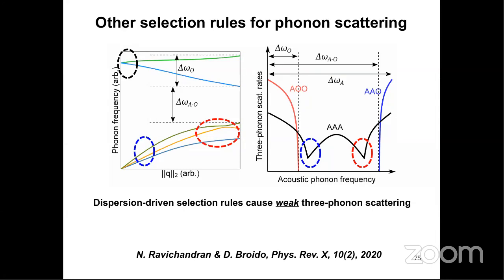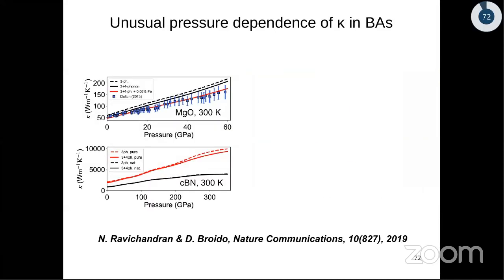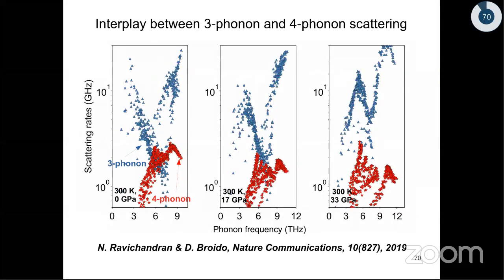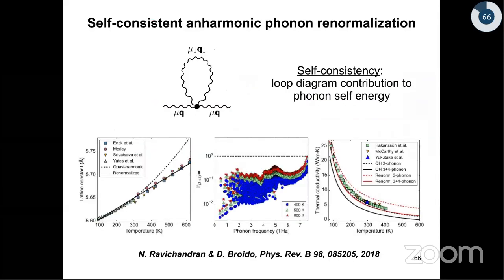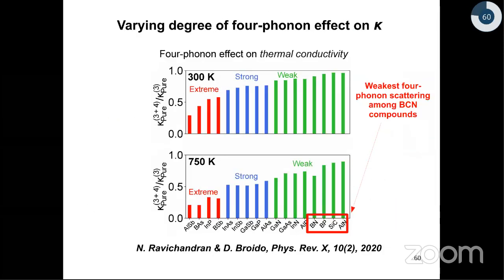What we find is in the case of 4-phonon scattering, the joint density of states is not sensitive to the specific features in the phonon dispersion. And additionally, we find that materials containing boron, carbon, and nitrogen atoms typically have weak anharmonicity. So with these 3 ground rules, we will be able to predict this plot, for example.